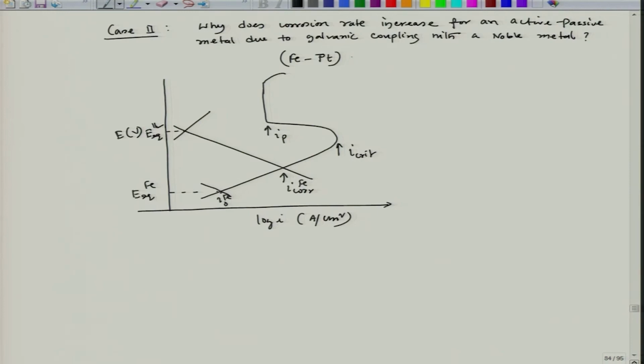Now once this particular alloy is exposed to acid, de-alloying effect starts taking place and redeposition of platinum takes place, so that you have platinum enriched zones on top of iron surface. Those platinum zones act as centers for increased hydrogen evolution, because the exchange current density of hydrogen on platinum surface is much higher than that of hydrogen evolution on iron surface.